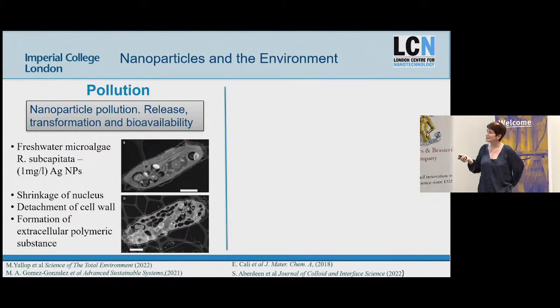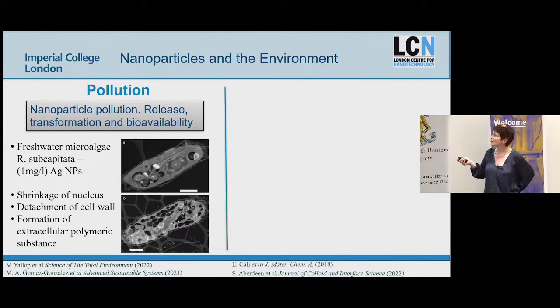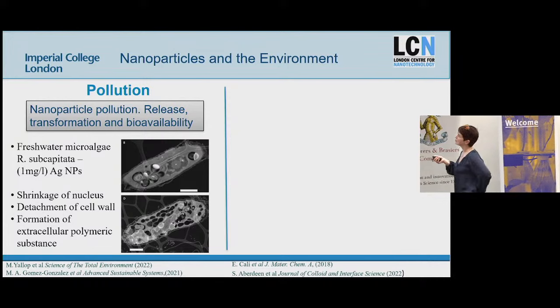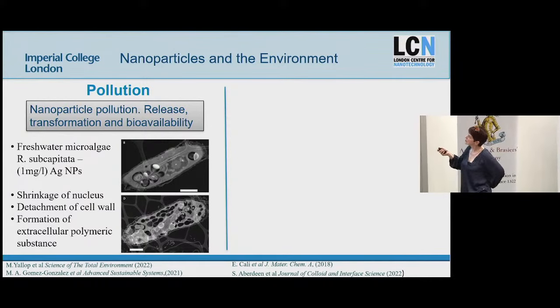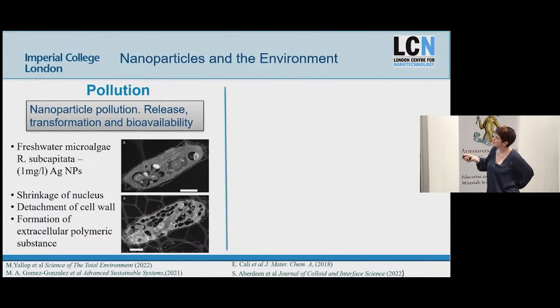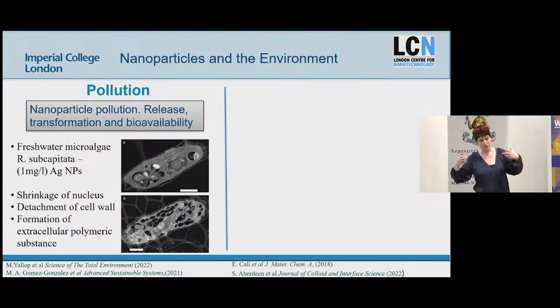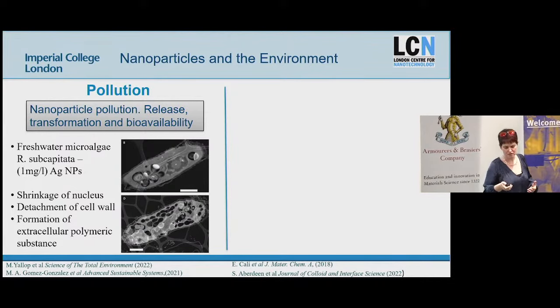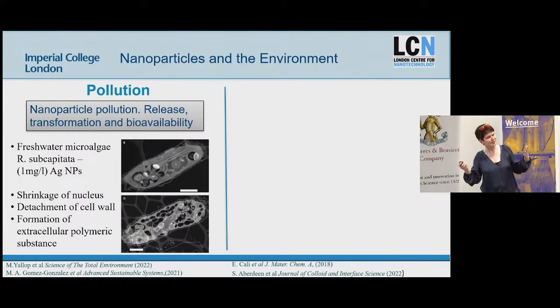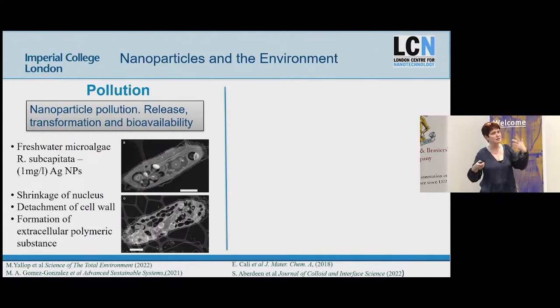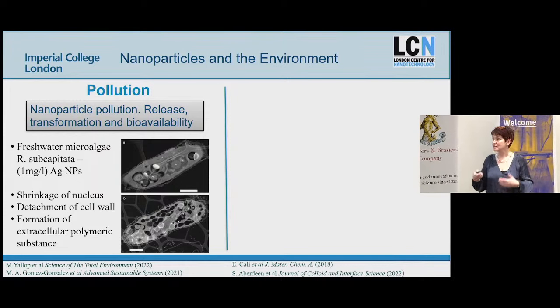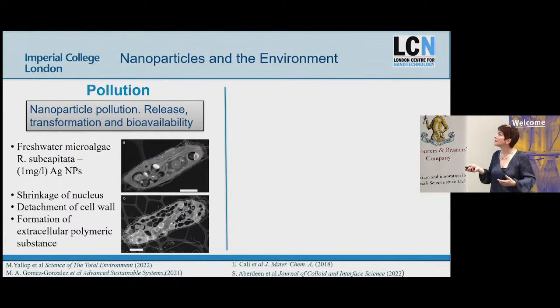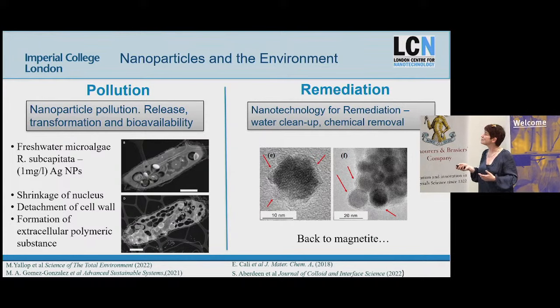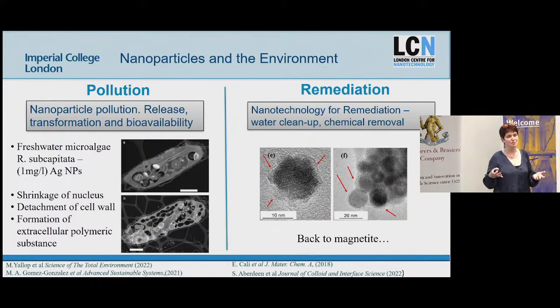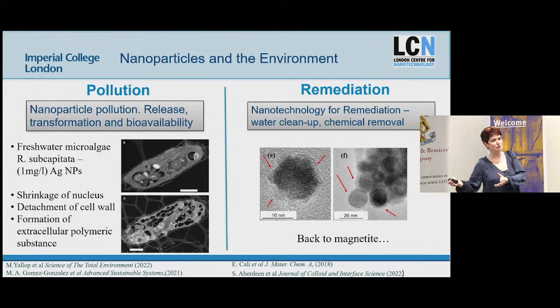This is work done with our collaborators in Bristol, Marianne. This is a happy one. This is one we gave some silver nanoparticles to, and you can see the change in the structure. The nucleus effectively shrinks, the cell wall starts to detach. So it's hugely impacted, and then the growth is destroyed. But for all the same reasons that we saw in the lung cells and the macrophage cells, it's locally delivering damage. But nanoparticles potentially also have great benefit for environmental remediation, right?